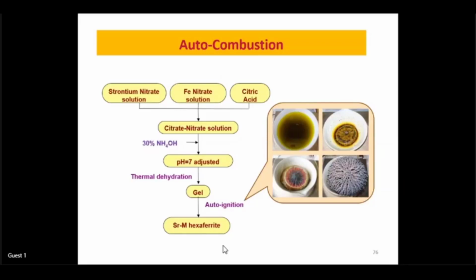So first is the liquid mixture, then heating is done. It is dry heating, no water was added in this. In the backside you can see the hot plate, then self ignition starts. Then you can see the material coming out, and at the right bottom, if you see, it is the final material, and that is nothing but this SrM hexaferrite, the M type of hexaferrite.